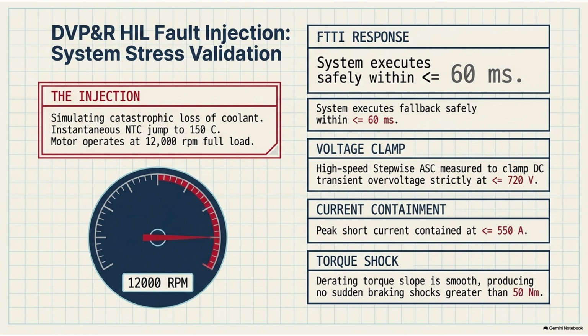The chips are dumping heat, the coolant is rushing through the microchannels, and then the engineers intentionally sabotage the system in real time. They inject fatal faults. They will flip a switch and instantly simulate a total coolant pump failure, bringing the forced convective cooling flow to absolute zero in a fraction of a second. Or they will electronically manipulate the NTC temperature sensor signal, forcing it to instantly jump from a safe 80 degrees to a critical 150 degrees Celsius, feeding the computer a phantom thermal shock.